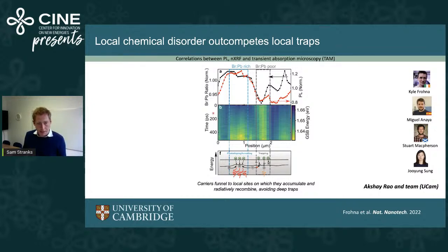And then this plot on the bottom here is a transient absorption microscopy map on the same region, where we're looking at the ground state bleach energy. This is essentially telling us about the recombination energy of these carriers, and we're looking over time after an optical pulse, in picoseconds. What we see is that in the region that's bromine poor or slightly iodine rich, there's not much change in the ground state bleach energy. It's really not shifting at all. It's already at a relatively low energy, which somewhat corresponds to an iodine-rich region.